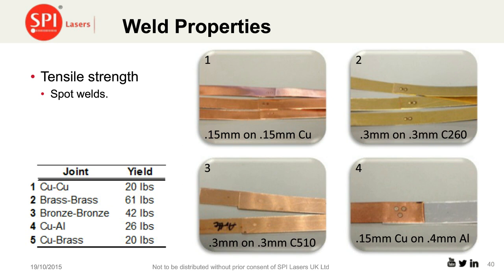So the key thing is knowing what these weld properties are. The strengths, for example, tensile strengths. And here we've got some examples of 150 micron copper to copper, 300 micron bronze to 300 micron bronze, 300 micron brass to 300 micron brass, and a dissimilar joint, 150 micron copper to 0.4 millimeter aluminium. And here you can see that the tensile strengths are quite reasonable for these kind of foils, and probably fit for purpose for a number of joint examples where these kind of metals could be seen in service.